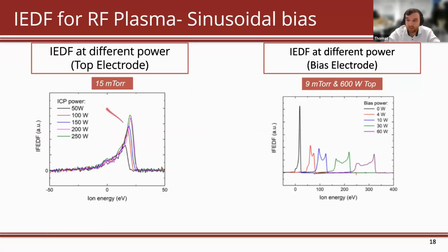And just to show this again, if you try to decouple it, say changing the ICP power, you do mostly increase the flux, but you slightly also increase the energy because the plasma potential is rising. And then in the case where you're just powering the bottom electrode, increasing the power massively increases the energy, okay? And actually, the higher the energy, the more broad the spectrum becomes. So if you're trying to do dielectric etch at 7 kV, 8 kV or something, this is a big problem, okay?